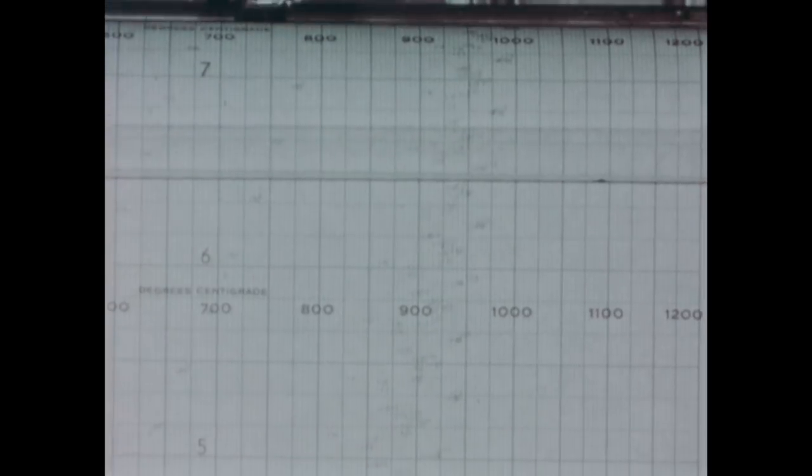The doors form a heat shield as well as a safety barrier. During brazing, the vented hydrogen continues to burn. Temperatures at the 24 thermocouples are recorded. It takes about 50 minutes to heat the 550 pounds of copper to 1,030 degrees centigrade. When all of the thermocouples read the same, the coils are carefully controlled to maintain that temperature for 40 minutes.